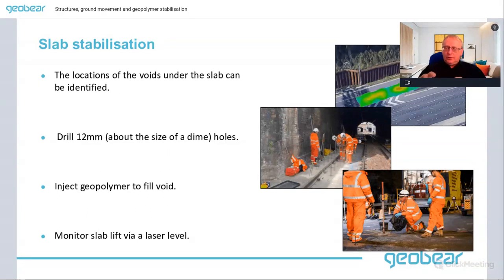And so this is how you would stabilize a slab with voiding: you drill a series of holes, you put in the tubes, you inject the geopolymer, and then you look for a surface reaction to know that once the voids are filled with polymer, and you know they're filled because you start seeing the ground lifting. And we can control the level of injection to less than 0.5 millimeter accuracy, because often we don't want to overlift if we want to maintain the same level. If there's been significant settlement, then we can over-inject and raise the slab to a new level, depending on what is required, what the target level is.